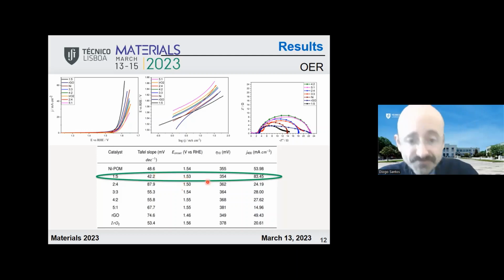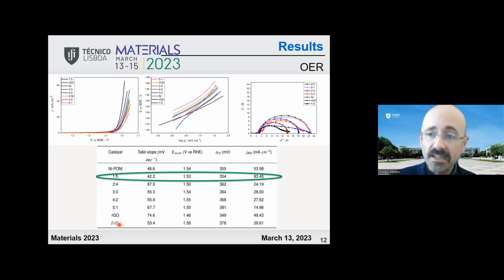It had also a low onset potential, and the current that was recorded at an overpotential of 400 millivolts was the highest. At 400 millivolts, we had over 83 milliamps per square centimeter, which was very interesting. This was even better than iridium oxide. Iridium oxide is the state-of-the-art material used for oxygen evolution reaction. It's an expensive material based on a noble metal, but it's widely used as the best material for oxygen evolution reaction. And in this case, we got better results for OER than benchmark iridium oxide.